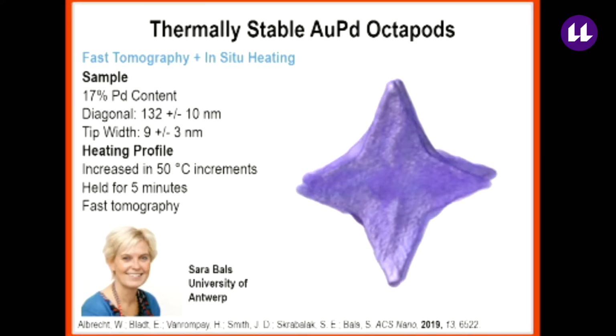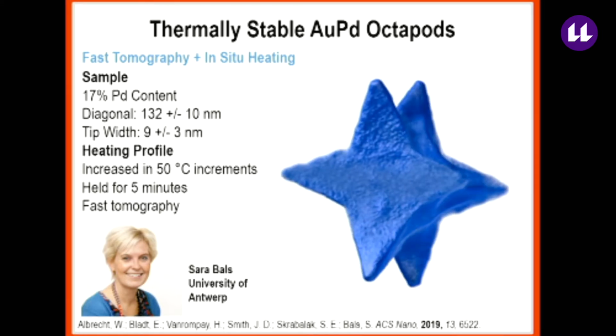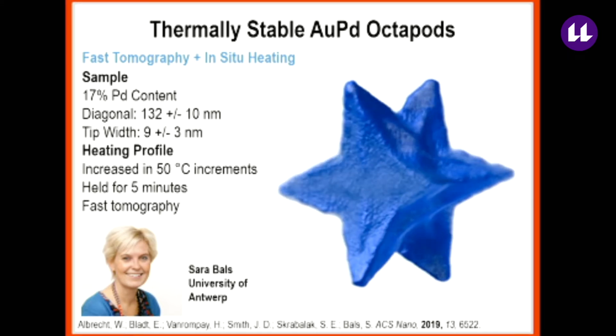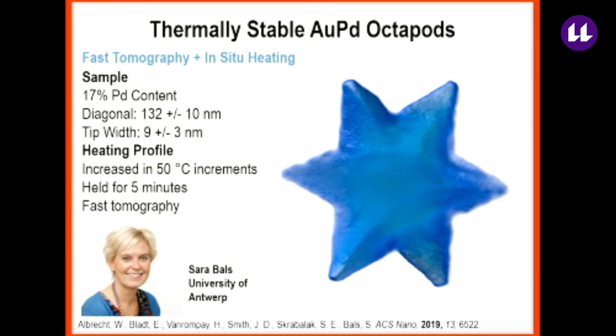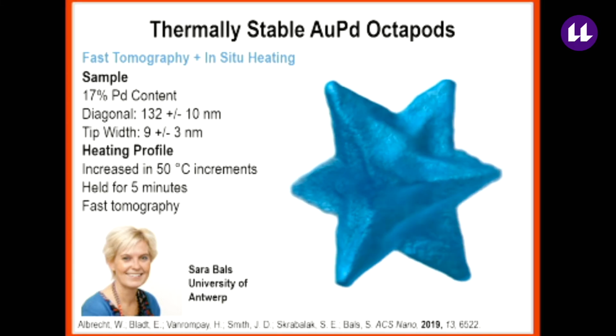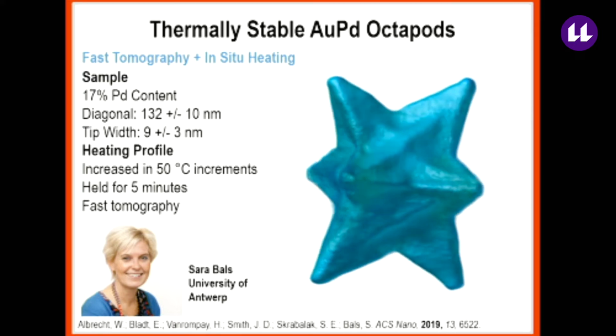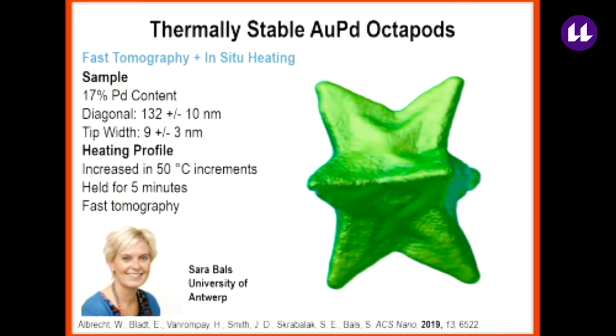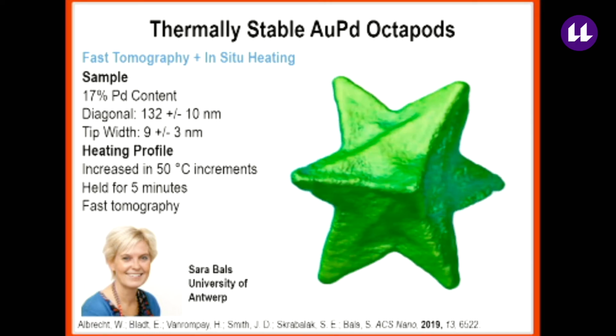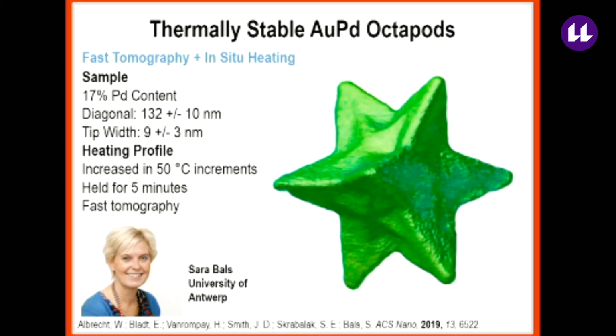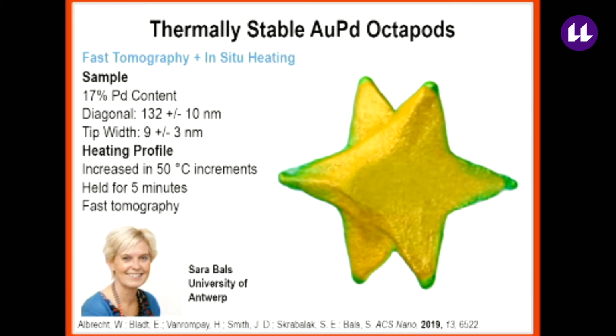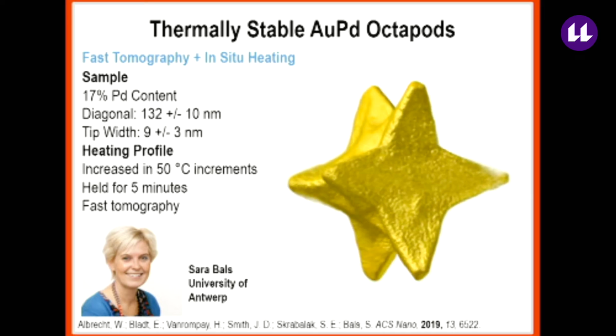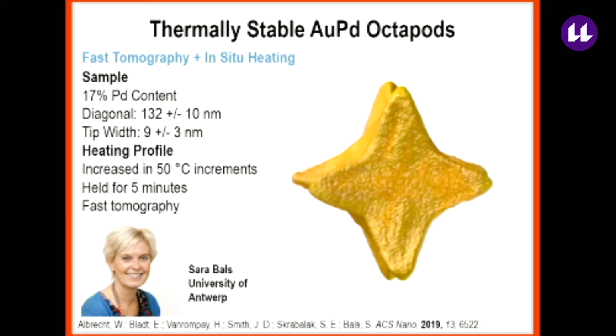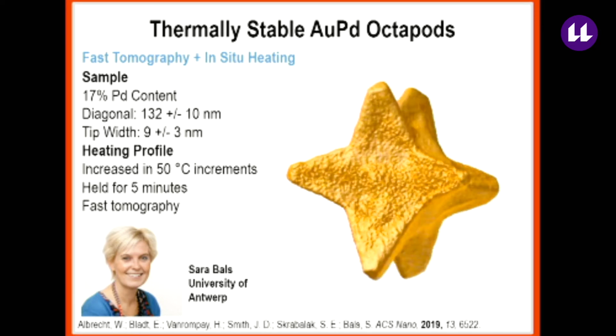And what I'm going to show you is a collection of these reconstructions, so the initial nanocrystal, and then every time there's a color change, that corresponds to an increase by 50 degrees. And as you're looking at this for a while, it looks pretty stable. The structure is being well maintained as it's being heated. And then eventually, you'll start to notice that there's some removal of material from the tips of the nanocrystal, so our high energy features. That volume is moving down towards the body of these nanocrystals.